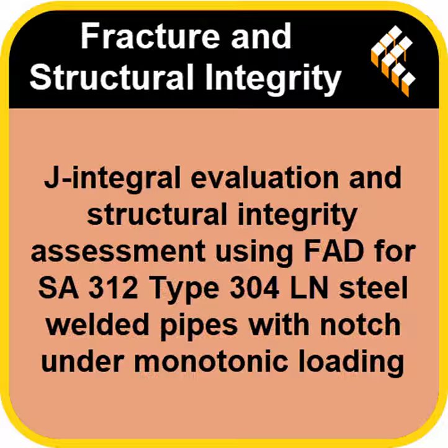Okay, so they calculated the points using different methods, plotted them against standard, well-accepted safety lines. What was the bottom line? What did they find? Well, when all the assessment points were plotted on the FAD using every combination of standardized lines and input formulas, the overwhelming headline finding was positive. In all assessments, all three pipe specimens, even with those massive simulated cracks, were found to be in the stable region. Okay, so safety achieved across the board. The FAD worked, the pipes were safe. That is the ultimate conclusion, yes. The components were assessed as stable.